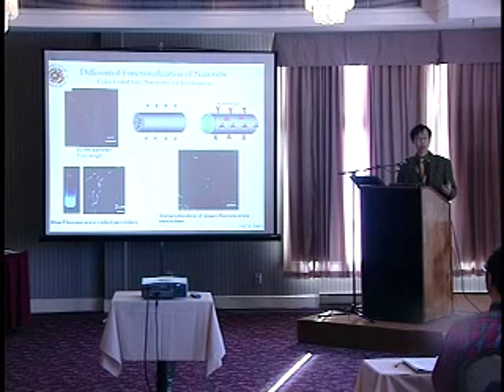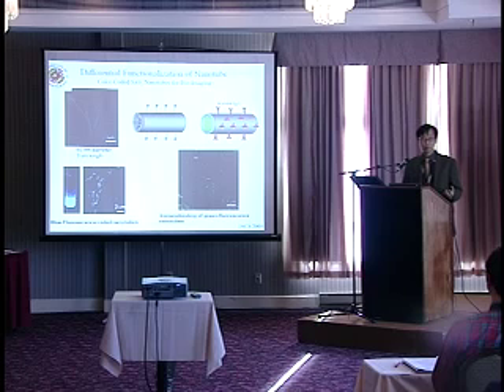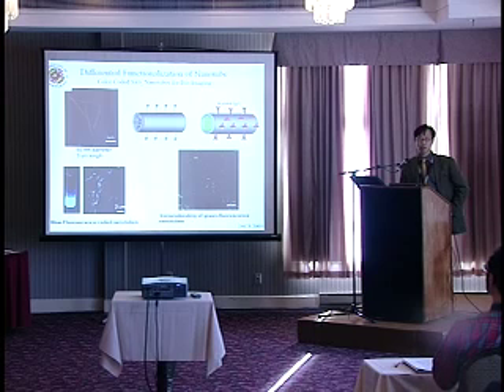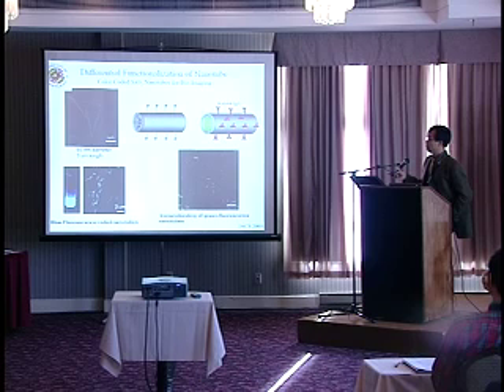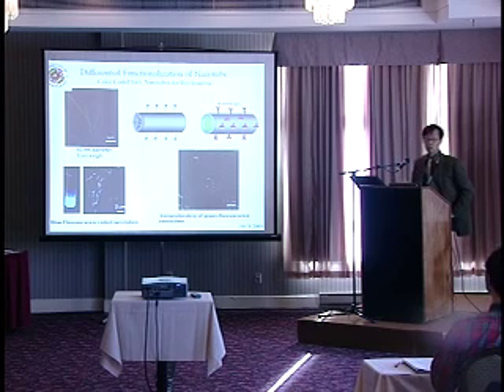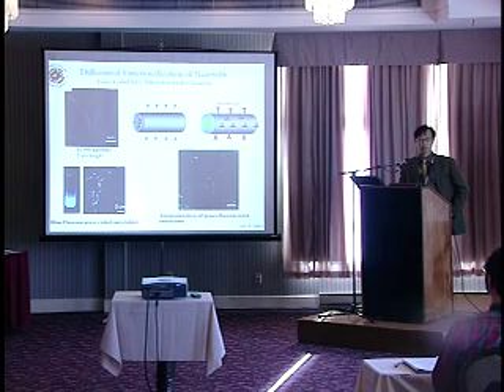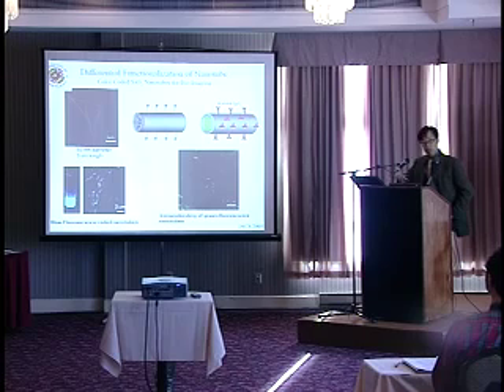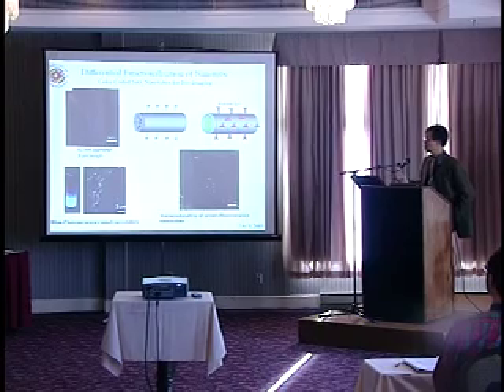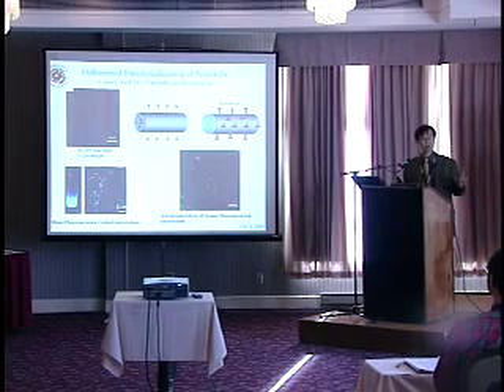The first important step to have multifunctionality in this hollow nanotube structure is differential functionalization between the inner surfaces and outer surfaces of the nanotube. So this is one example of what we did. We put lots of dye molecules inside of the nanotube and modify the outer surface with specific proteins, and then let them interact with another specific biosubstrate, and then rinse them out. Then you see these individual nanotubes fluorescing on the specific biosubstrate. So this is another beauty of template synthesis.